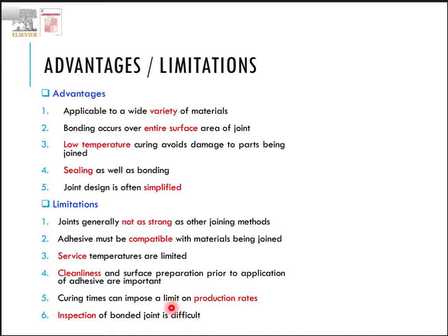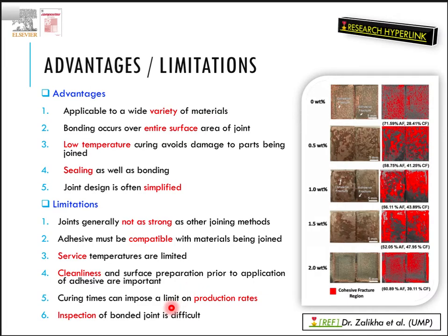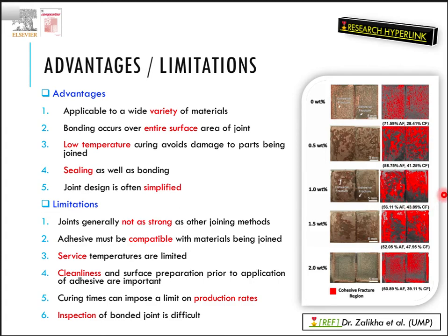There is a research reference on the influence of aluminium oxide nanoparticles on the adhesion and thermomechanical properties of epoxy adhesive. Basically, the authors joined two adherends using an epoxy adhesive and increased the concentration of alumina oxide nanoparticles within the epoxy. They observed that as the concentration of alumina oxide increases, the joint strength increases.